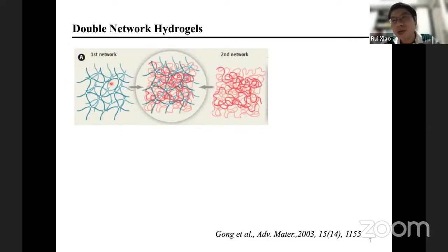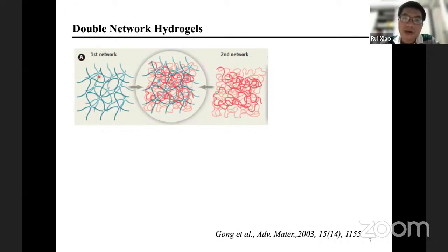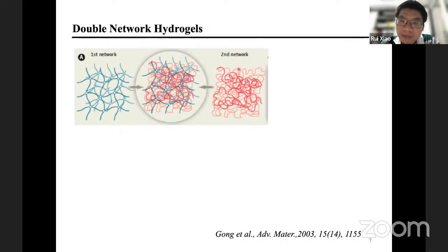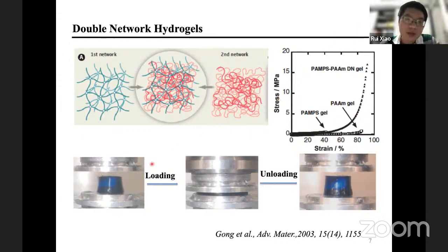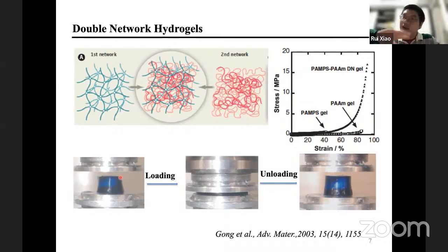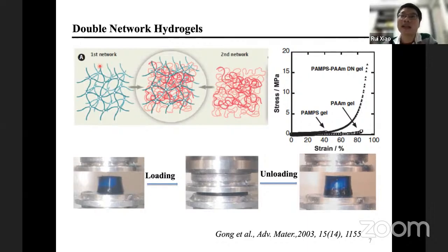I'll introduce double network hydrogels - many people are familiar with this material, initially proposed by Jian Ping Gong from Japan. You synthesize a first network, put it in solvent again, and chemically synthesize a second network. The second network is very loose. For each pure network alone, the mechanical property is not strong, but if you have a double network the mechanical properties can be significantly enhanced. When compressed to very large strain and unloaded, the material doesn't break, whereas each pure network shows brittle failure.